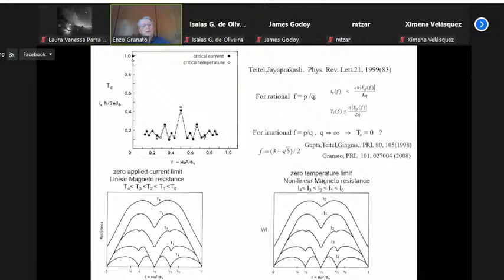Now, as just shown, the ground state is strongly dependent on the frustration parameter. The critical temperature obtained by Monte Carlo, as indicated here in the figure on the top left, is strongly dependent on the frustration. As we can see here, the Tc, the open symbols, is strongly dependent on the frustration, and the critical current also depends strongly on the frustration.